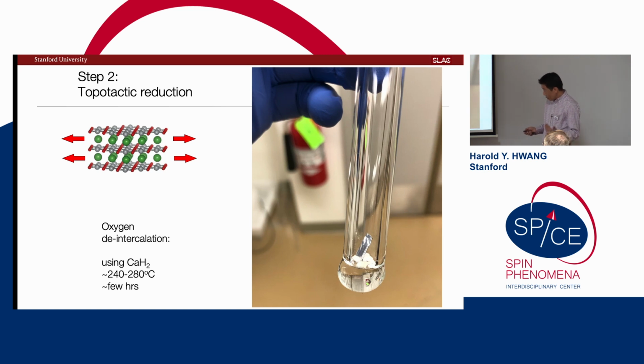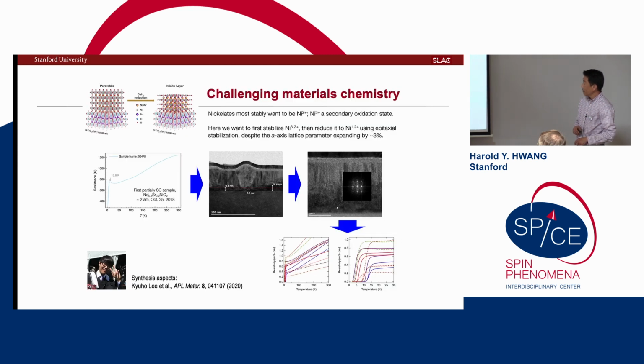And so again, it's a low temperature game. This is like 250 to 300 degrees C, where we can kind of slide out the oxygen and maintain the structure to some degree. Right? That's why this language of topotactic the chemists have been using. Okay, so again, this is all games in metastable materials. It's quite a challenging chemistry to deal with.